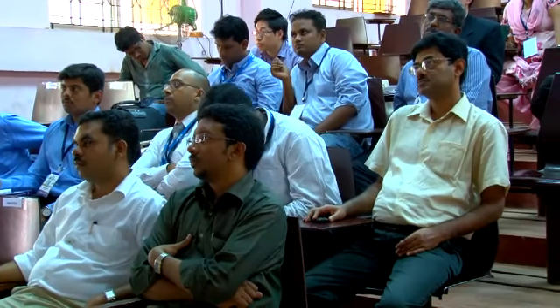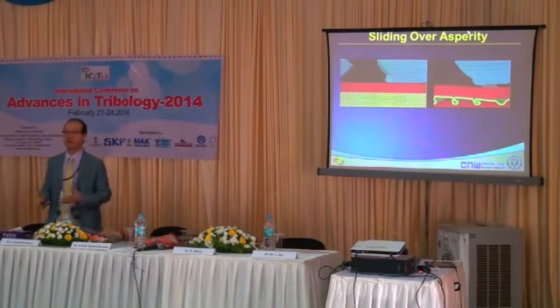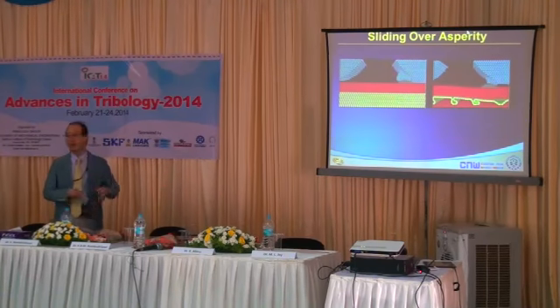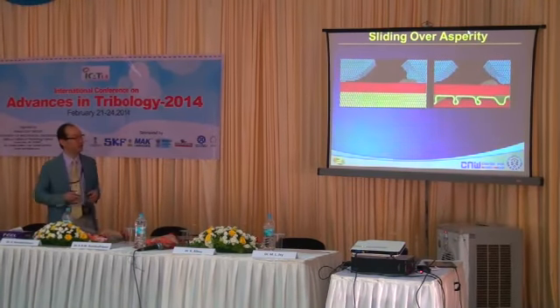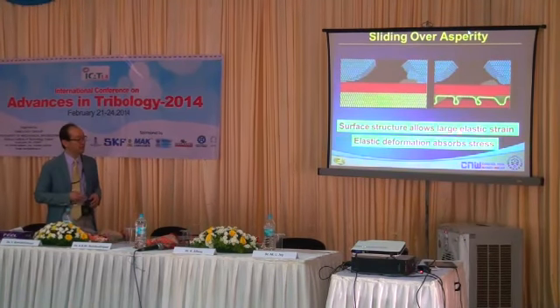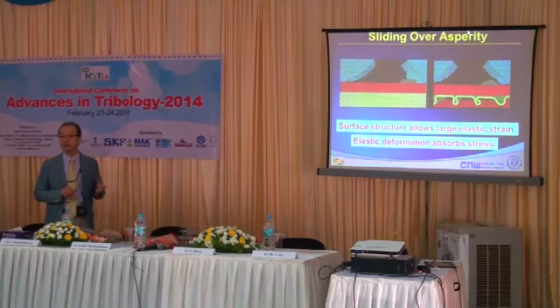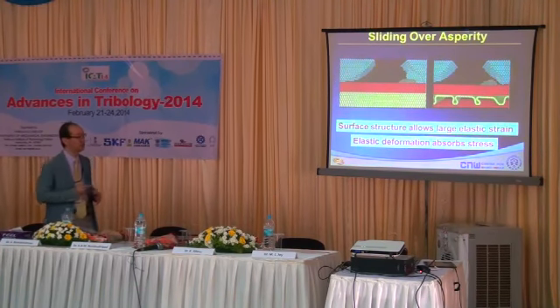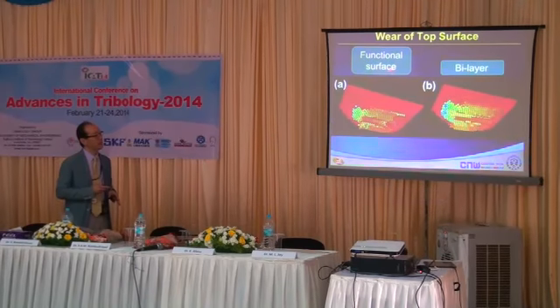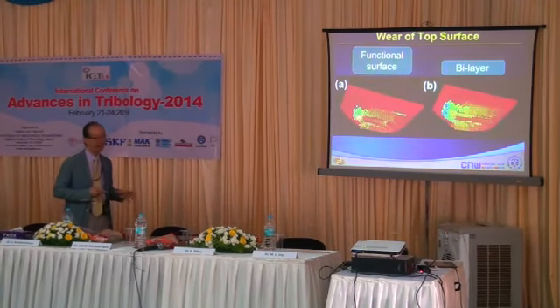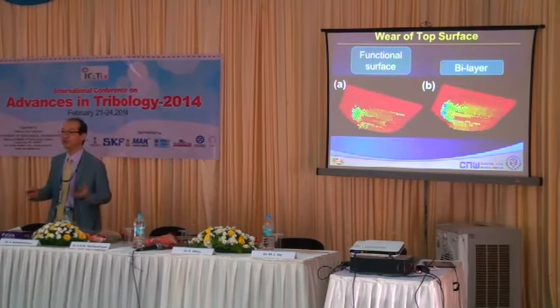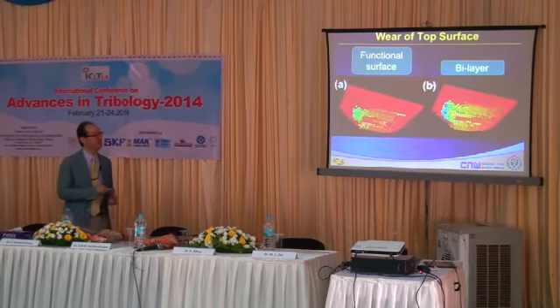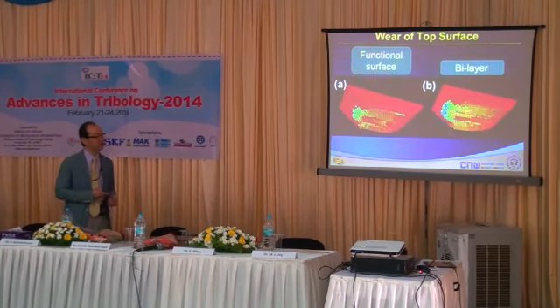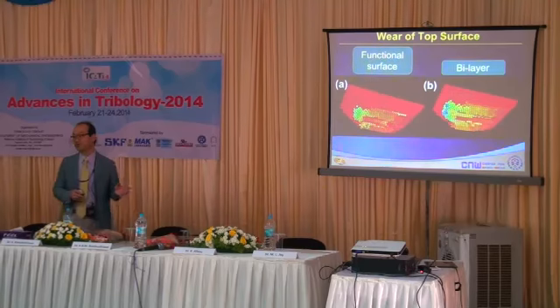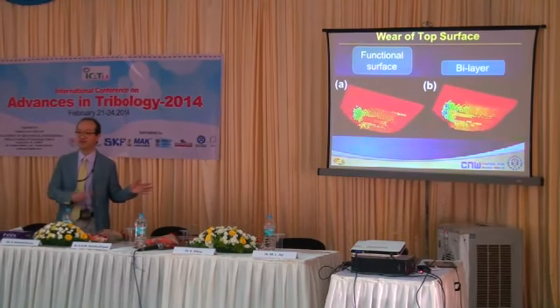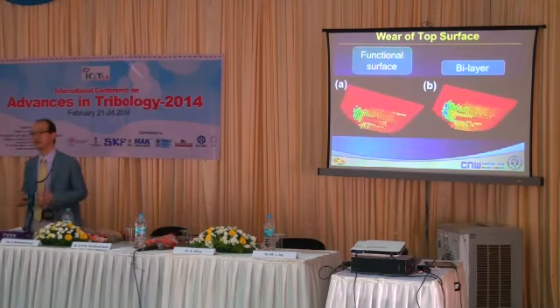You can see that in the case of the corrugated surface, it is able to accommodate the deformation caused by the presence of this asperity largely by elastic strain, and thereby absorbing the energy. So the surface structure allows large elastic strain, and the elastic deformation absorbs the stress which would otherwise be used to destroy the surface. And we compare the top surface in terms of the wear, and we count the number of atoms that have been removed from the initial position, which we quantify as wear. Compared to the bilayer, where you see a lot of displaced atoms at the top surface, you see a relatively smaller number of displaced atoms. And we're using this kind of result as an indication that the structured surface performs better in terms of reducing the wear.